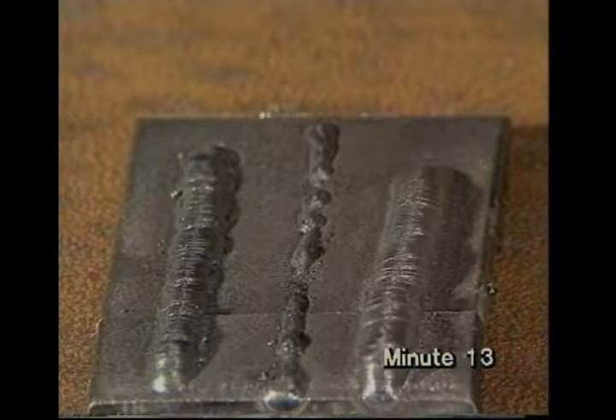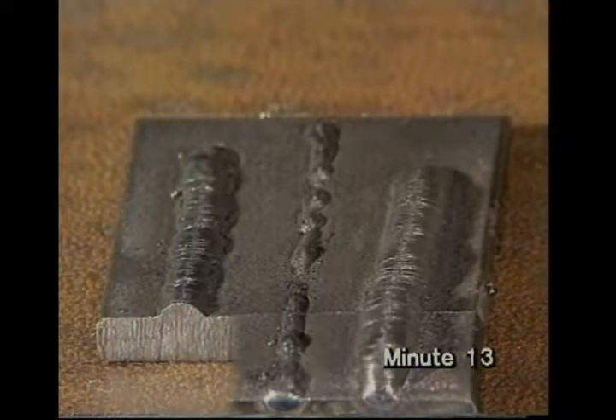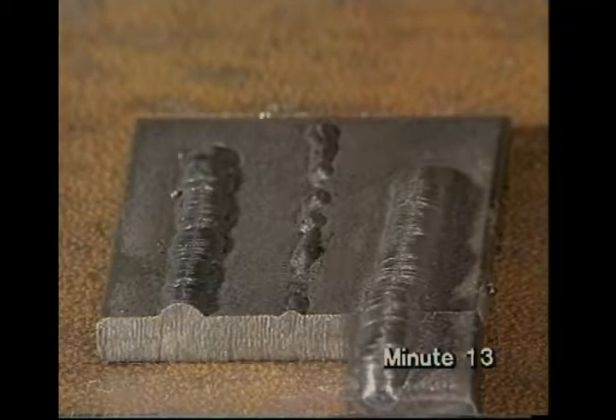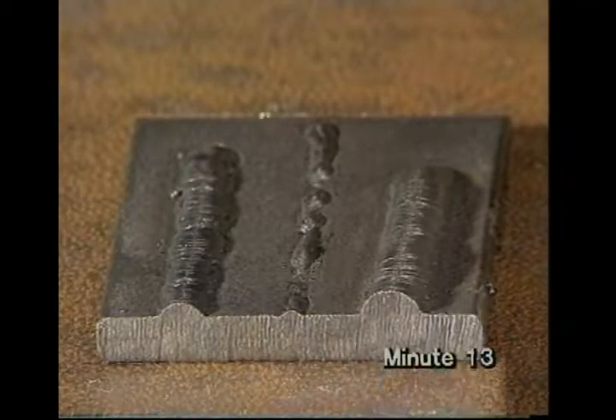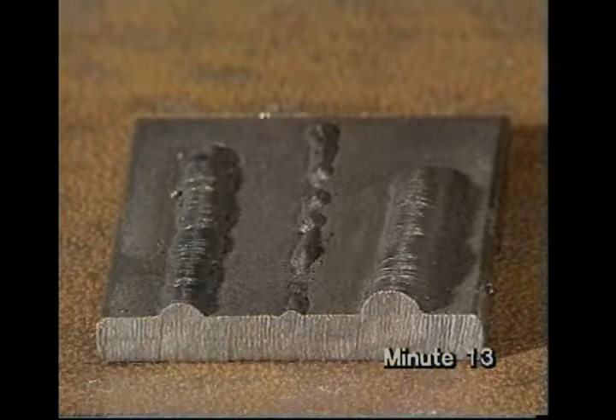Keeping the right travel speed is important. You may be going too fast. But if you go too slow, the weld metal piles up and may put the arc out. The beads clearly show the problems. Normal speed? Fast, small and stringy. Slow, large and lumpy.